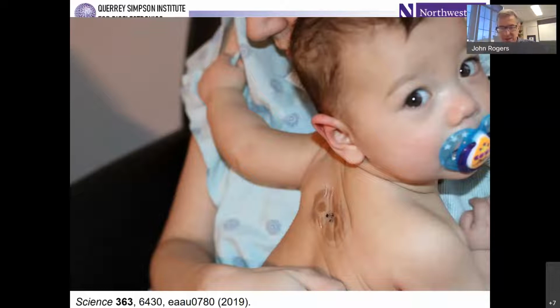They're very skin-like, and so the interface stresses associated with motions of the skin provide only a very small driving force for delamination. So even a mild adhesive is good enough. And of course, you don't have a wire tugging on the devices, which is also important. So we can use an adhesive that has an adhesive strength about 10 times lower than that associated with the adhesive tapes that are used to keep the traditional wired biosensors adhered to the skin. So that's what it looks like.